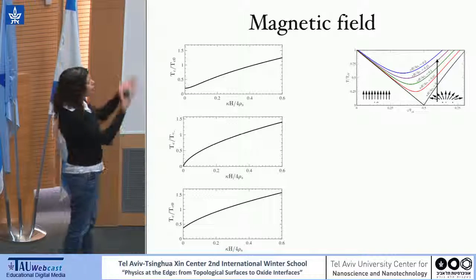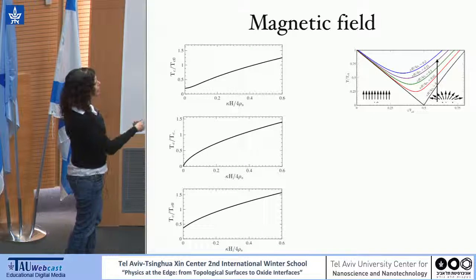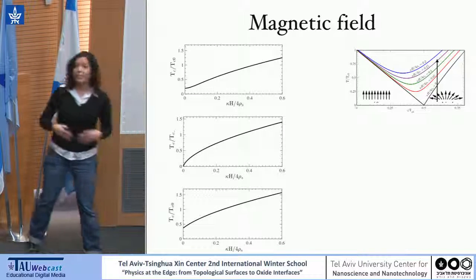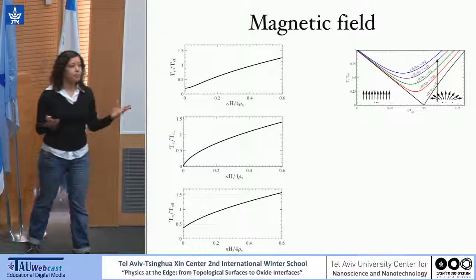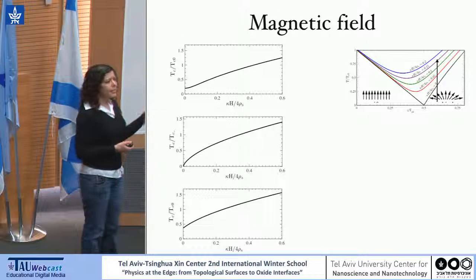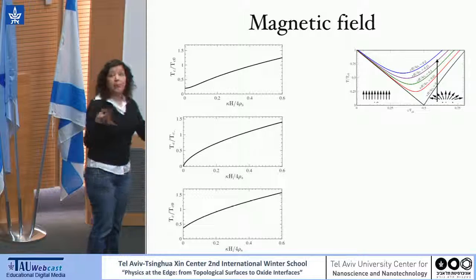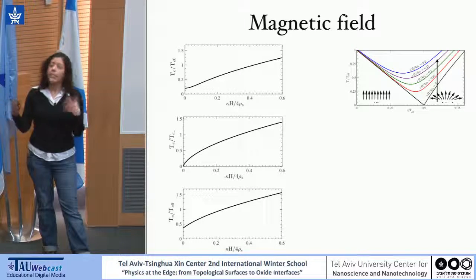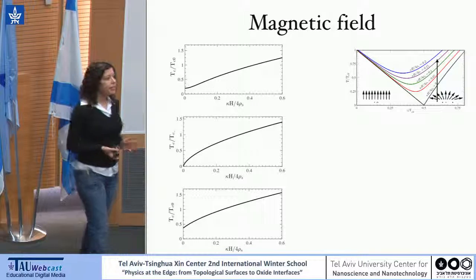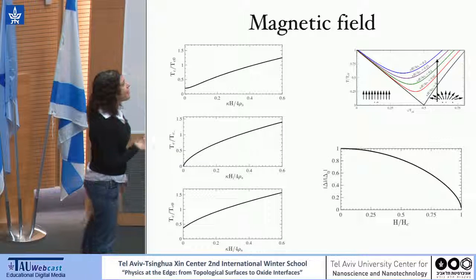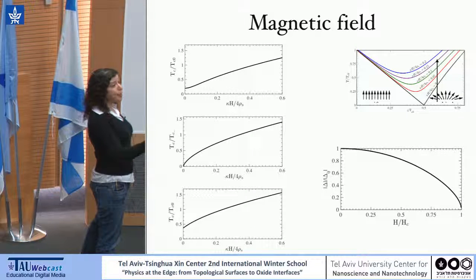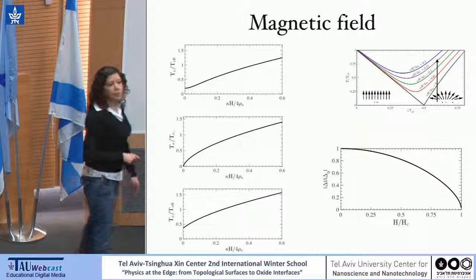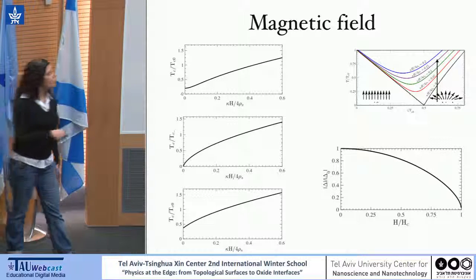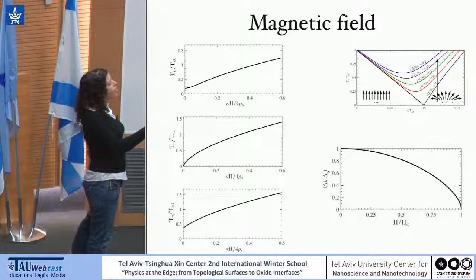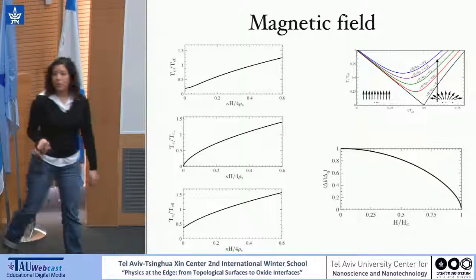Now, all that I was showing here, it looks like Tc is just going to increase and increase without actually decreasing. Obviously, it is under the assumption that the order parameter, the mean field order parameter, does not change much with magnetic field. Eventually, obviously, if you look at the order parameter, the mean field value, as a function of magnetic field, eventually it will go down. But one can imagine convolving these two plots and getting this kind of non-monotonic behavior.